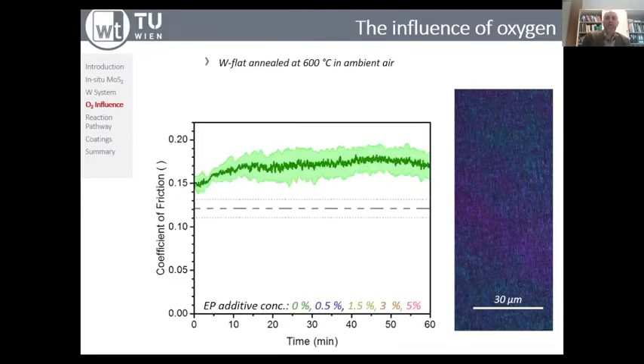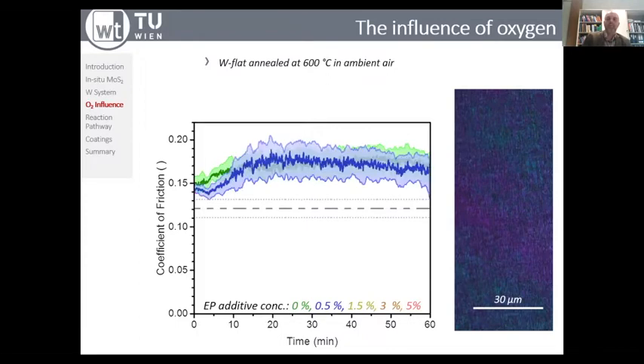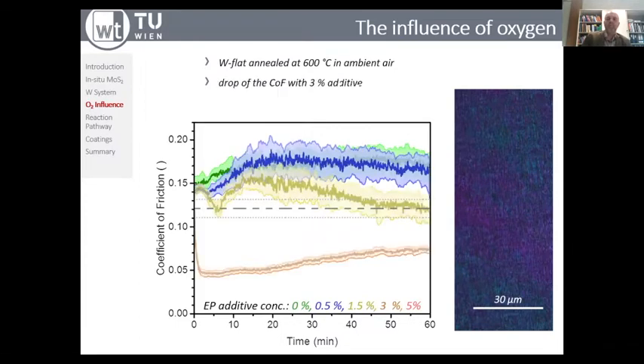And again, we start at 0%, there is no EP additive present, coefficient of friction versus time. Now we start to add slowly, step by step, the additive. And what you see is first, nothing happens, but then for higher concentrations, once you reach a certain threshold, there is a significant jump of the friction coefficient down to very low values, up to 0.05, which is rather small. So obviously, when you reach a certain threshold value of the additive concentration, then you have a very pronounced and emphasized drop in the coefficient of friction.